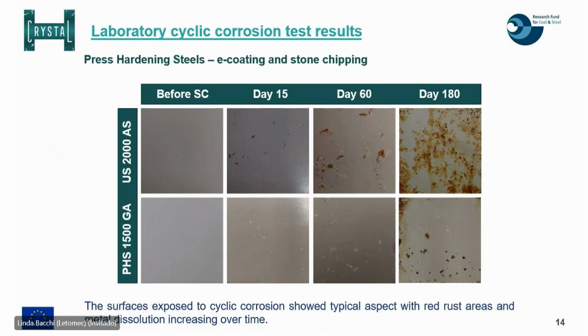Here, just as an example, because samples were very, very numerous, we reported here for the PHS steel only some images from the testing. In particular, we have selected the samples after e-coating and stone chipping. And as you can see here, over the time it is very clear how we can appreciate the increasing of the red rust. And also, I can tell you that we appreciated also the metal dissolution of the material. But however, in all the cases, the diffusible hydrogen content inside the sheets was very low.